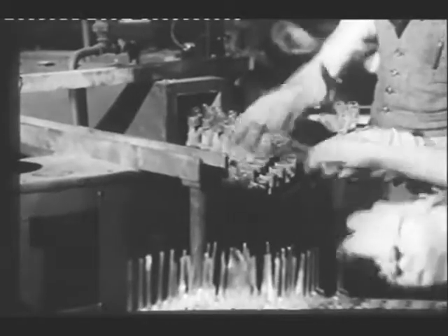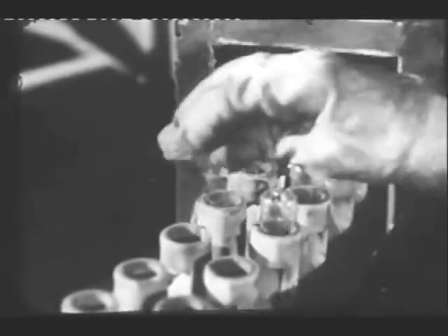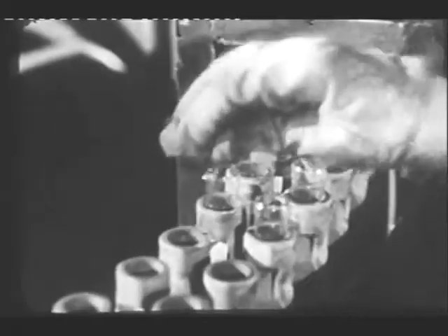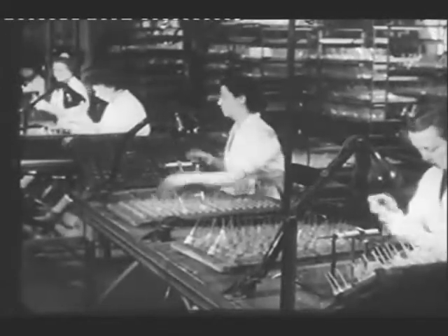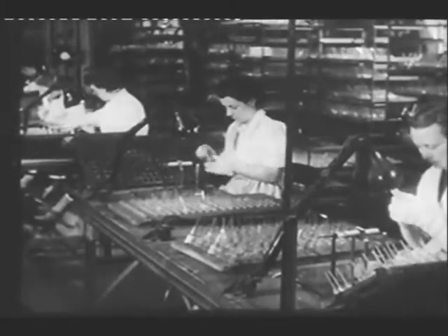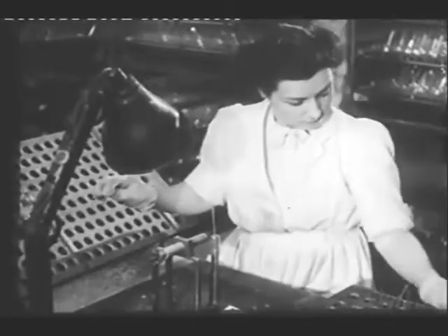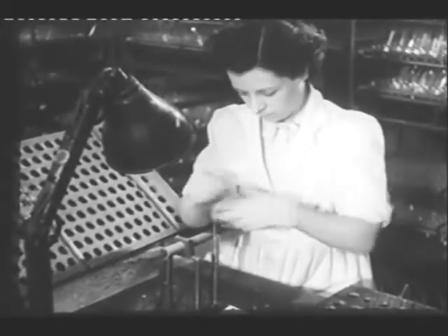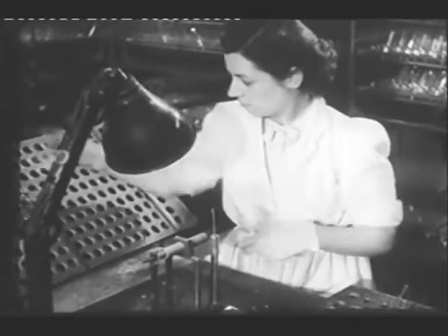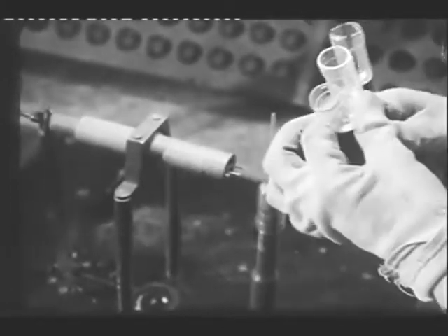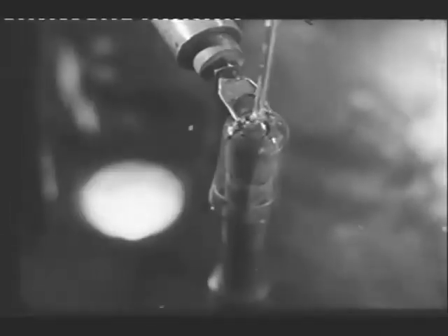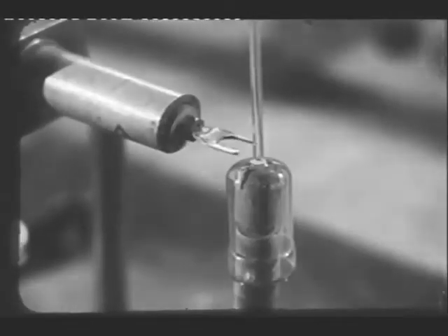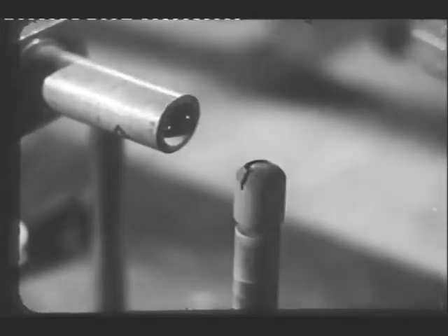After each stage in which glass has been worked, it is annealed by raising it above a certain temperature and then cooling it gradually, thus normalizing any strains set up in the material. Each bulb is inspected, and any which show defects are ejected. In this test equipment, a high-tension discharge is produced between two electrodes. When a good bulb is placed over the probe, the spark is extinguished. But if there is the slightest crack or flaw, the discharge sparks through, the faulty bulb then being rejected.